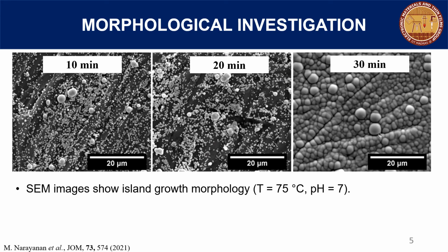In order to study the morphology of the coatings, SEM images were recorded. These images show an island growth morphology. Initially, small islands of nickel phosphorus are formed, and these come together as the time duration increases to form a uniform coating.